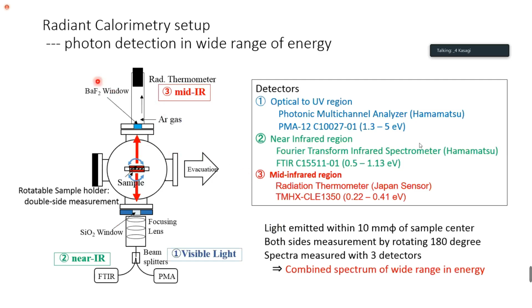So now, this is our experimental setup to measure a wide range of photons, from, let's say, 0.22 to 5 electron volts. We put 3 detectors: one for the optical to ultraviolet region over here, and 2 for the near-infrared region. This is also the spectrometer, a Fourier transform infrared spectrometer. And the other one is the mid-infrared region. This is just a radiation thermometer though. Combining these 3 measurements, we can get a very nice spectrum over a wide energy range.